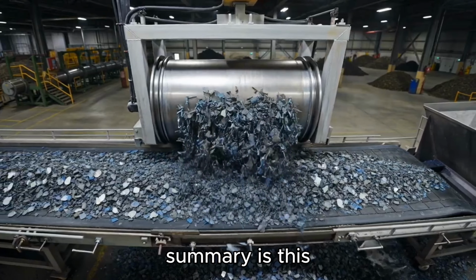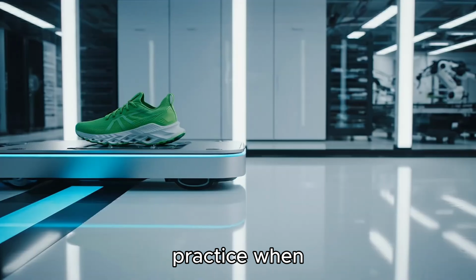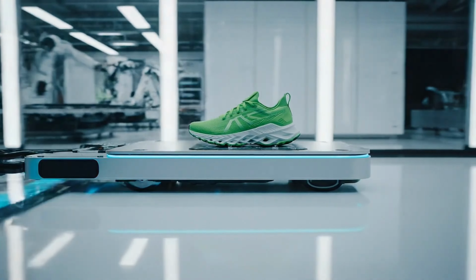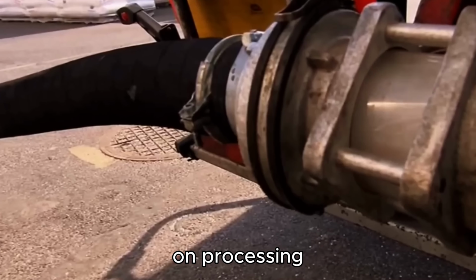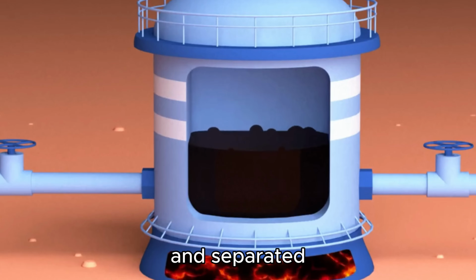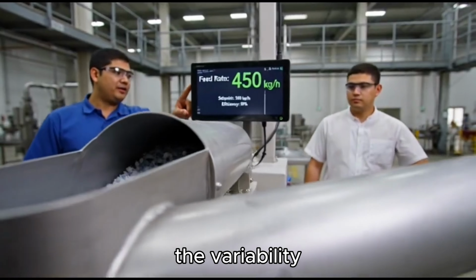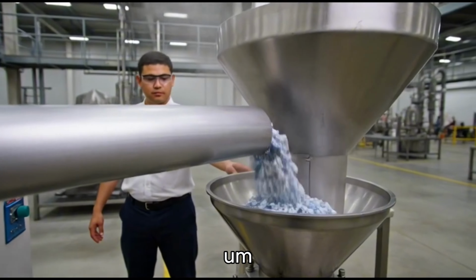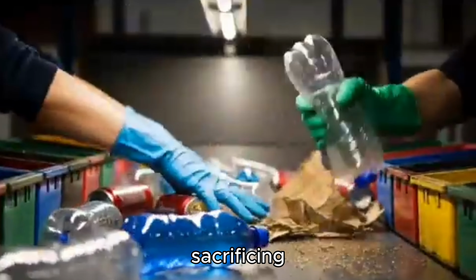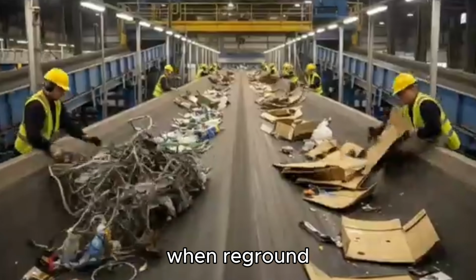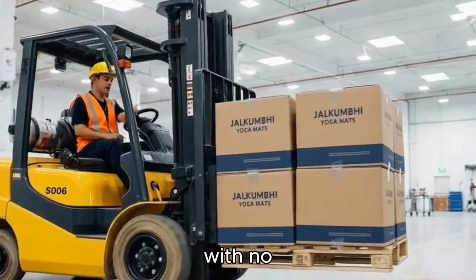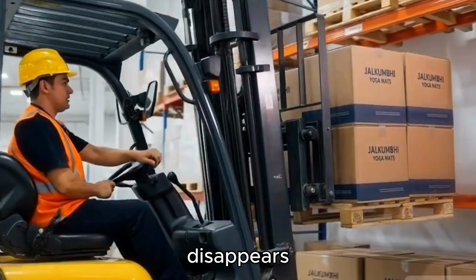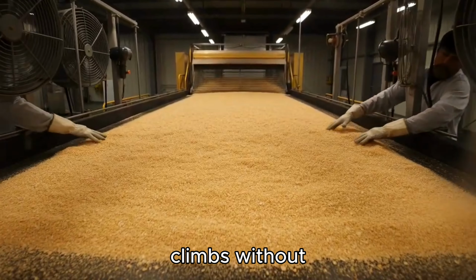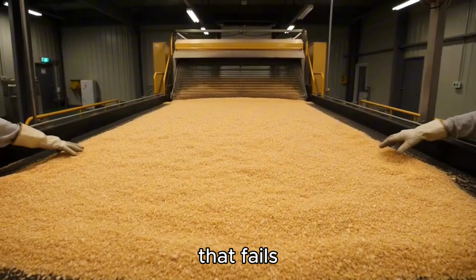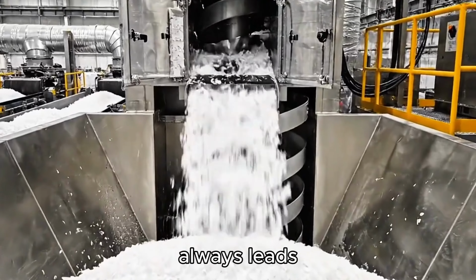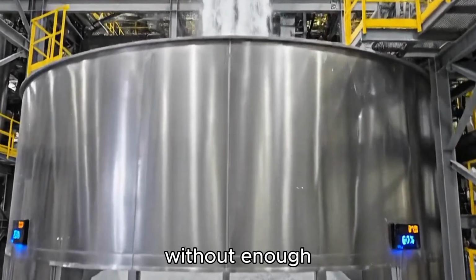The honest summary is this: regrind is a mature, well-understood practice when manufacturers treat it with the discipline it requires. Track the material, define hard limits on processing cycles, keep your material streams clean and separated, know which applications can absorb the variability and which ones genuinely cannot. Those factories run efficient operations without sacrificing part quality. The failures happen when regrind gets treated purely as a cost line item with no supporting infrastructure. When the tracking disappears, when the bins get mixed, when the regrind percentage climbs without documentation, you eventually produce something that fails in the field. And the investigation always leads back to the same place, a granulator that was running without enough oversight.